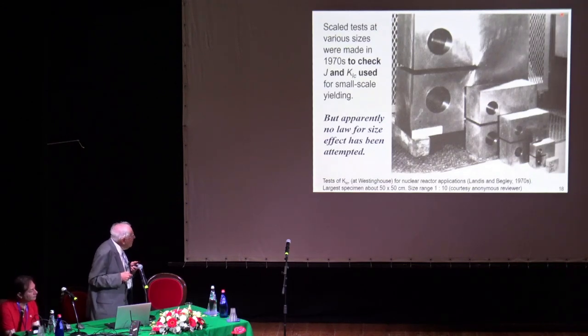A reviewer sent me a picture of a test which was done at Westinghouse in the 1970s, and at that time they put, as you see here, scaled specimens, and the only thing they looked for is the size for which linear elastic fracture mechanics works. So they determined that testing of linear fracture mechanics, which means measuring stiffness of the specimen as a function of crack length, gave correct results equal to the J integral. Interestingly, at the time, nobody was interested in size effect, of course, so they did not publish it. We don't know what the values are here; it would have been very useful. They only looked at the larger specimen.